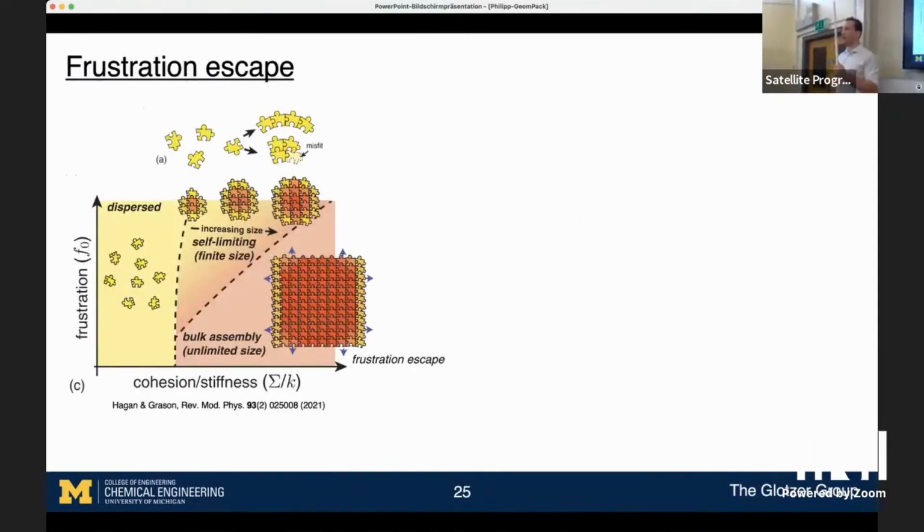Okay, so now we know maybe the fundamentals, that there are some crystals which we can think of as minimizing free energy because they can be seen as defect structures of the tessellations, and some which do this uniformly because the curvature mismatch is too large, so this whole mechanism breaks down.